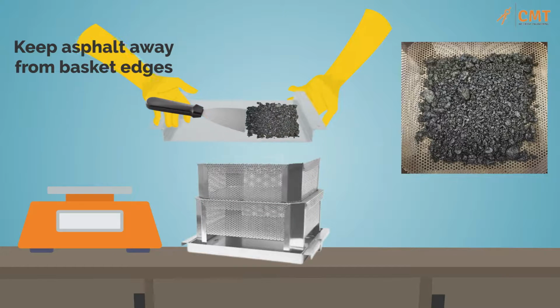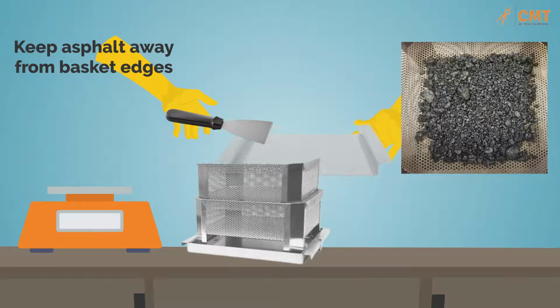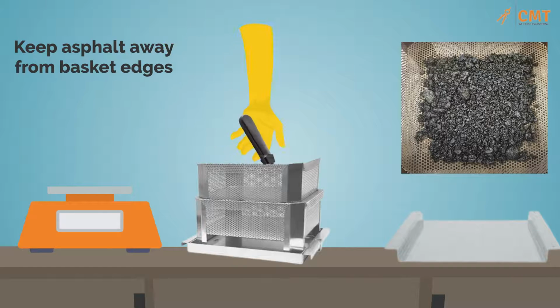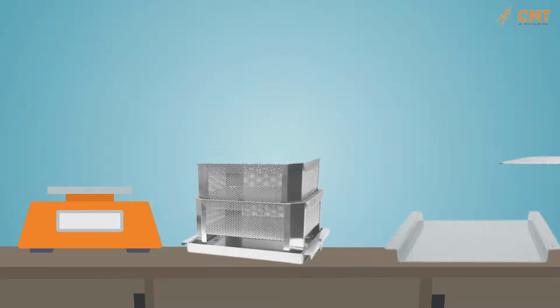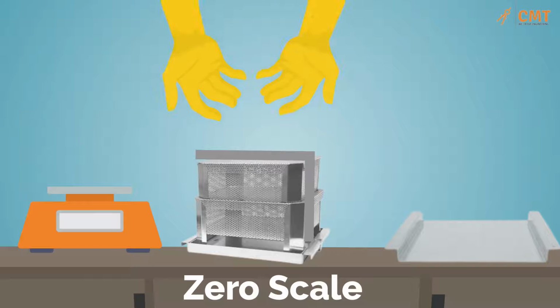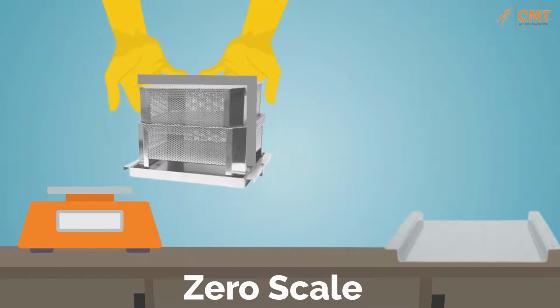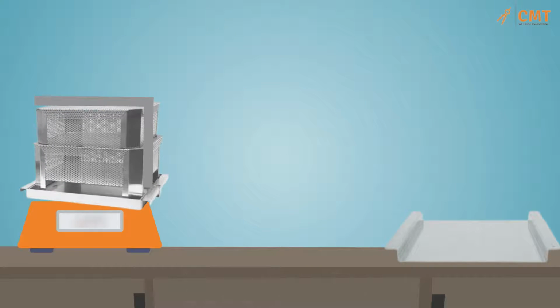Now you will place the remaining half of the sample in the top basket. Then make sure to evenly distribute the sample and move the mix away from the basket edges. Then you can complete the basket assembly by securing the lid and assembly guard. Next, you need to zero the scale and place the basket assembly on the scale platform. Then record the total mass of the basket assembly and sample.